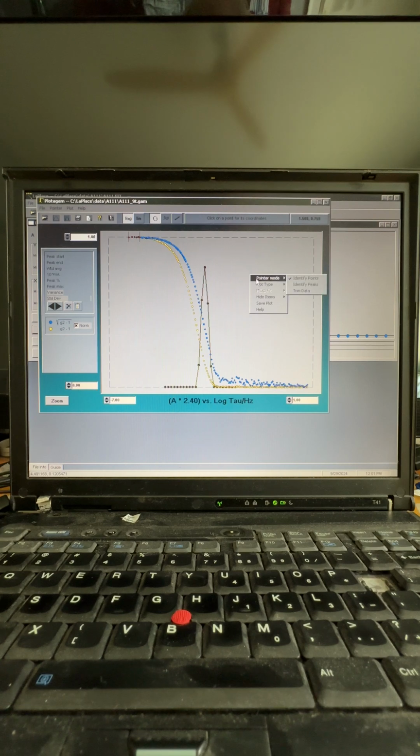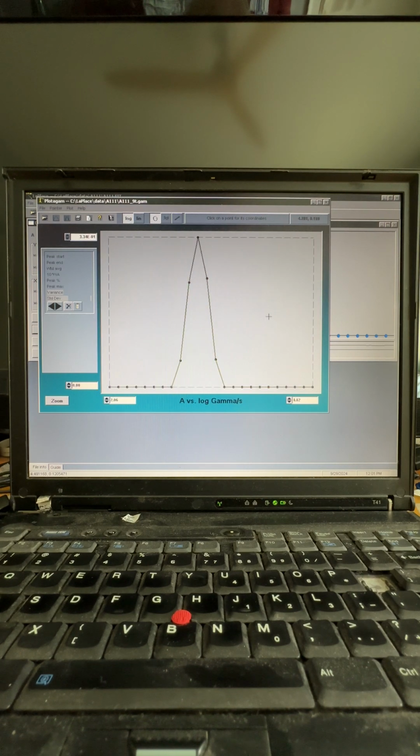I have to go to a different mode to see it. I think this will be the best one for that. By the time you get to doing this content type analysis, you definitely should have been running cumulants, of course. Yeah, in the ALV world, that happens automatically. But you also should have run a multi-exponential fit, and a single exponential fit is probably where you would have stopped in this case. So you would know what that decay rate was, okay?